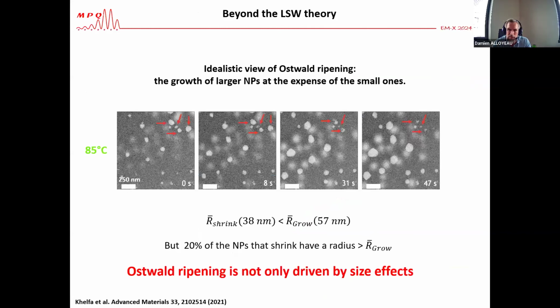So we also have studied during this experiment the Ostwald ripening of nanoparticles, that you can clearly observe when you go at high temperature, like at 85. And the common view of the Ostwald ripening is the growth of large nanoparticles at the expense of the small ones. So you expect the small nanoparticles to shrink and the large nanoparticles to grow. And when you observe what's going on inside the liquid cells, you realize that this is true.